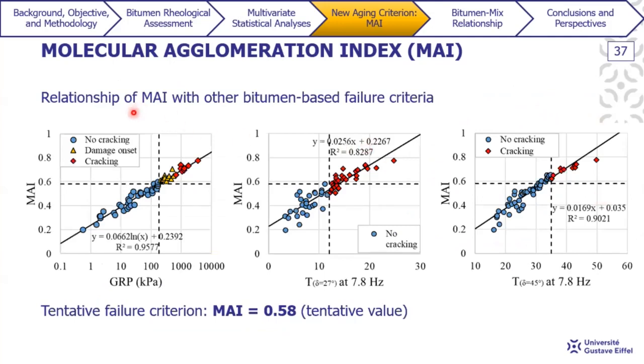Now I present the relationship of MAI with other bitumen-based failure criteria. We have MAI versus the Glover-Rowe parameter, and MAI versus the temperatures corresponding to 27 degrees and 45 degrees phase angle, both at 7.8 hertz. And we can see that we have good correlations here. We also took advantage of these criteria since they already had a limit value, to determine our own. In this case, we could propose a tentative failure criterion for MAI of 0.58. This criterion could be updated once we have more bitumens in our analysis.